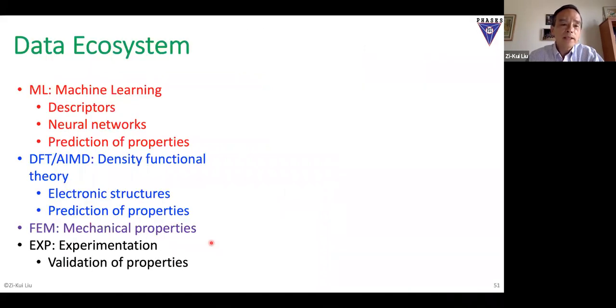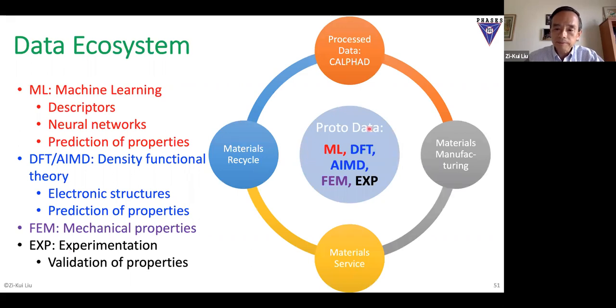And so this one, basically I want to mention the data ecosystem. So the machine learning, you develop the data, then the DFT. Machine learning now is the most efficient way to produce data, but you need to input the data, right? So you can do DFT data or ab initio molecular dynamics to confirm those data or generate data for the machine modeling. Then it goes to the FEM, which we are working on too, to predict mechanical properties. And then you do experimental validation of the properties. So in that case, I will call it proto data. Proto is original data for machine learning, DFT, MD, FEM and experiment.